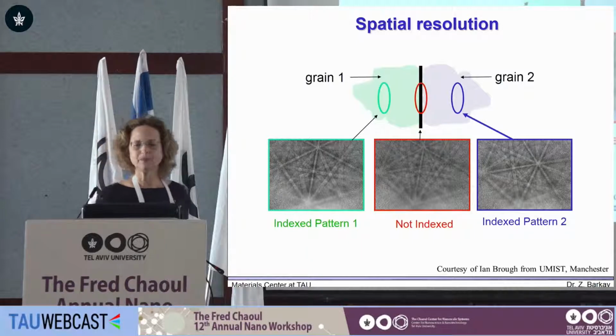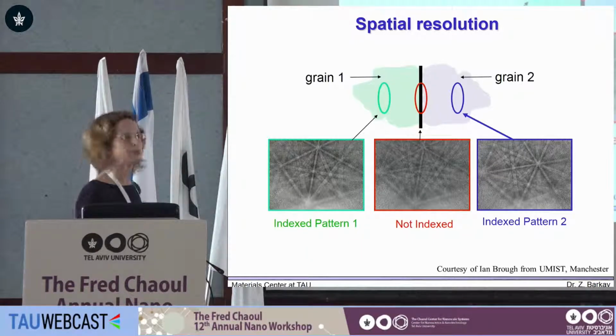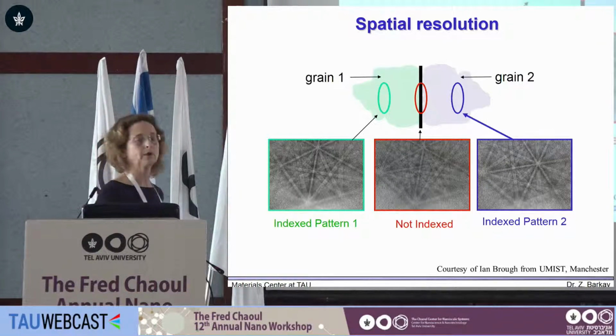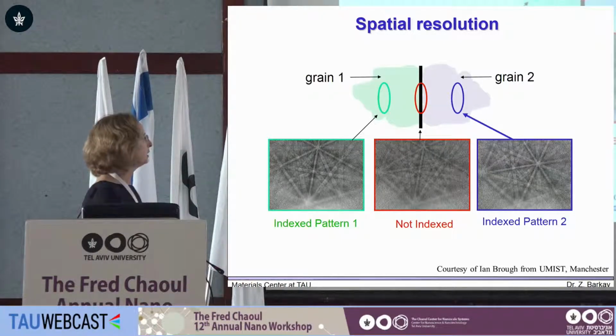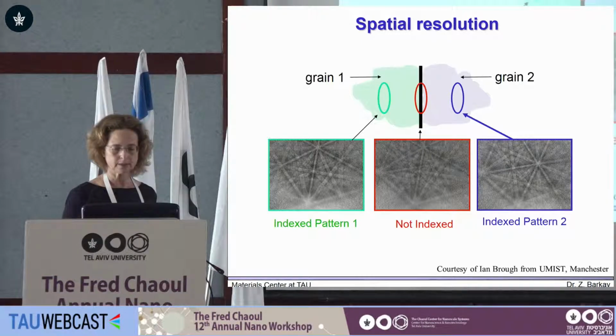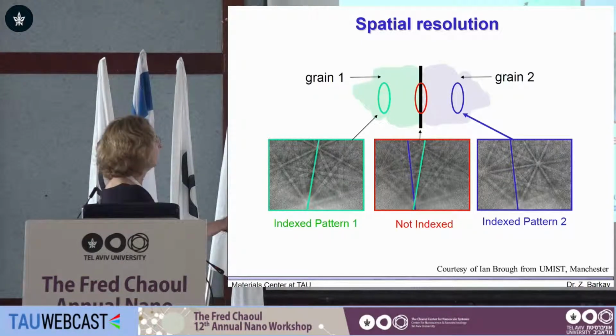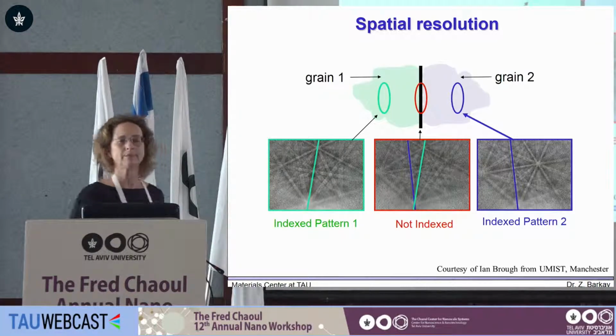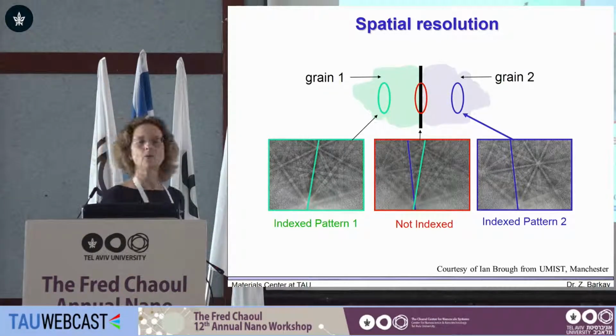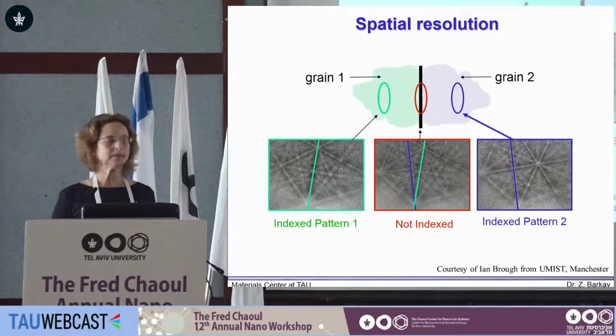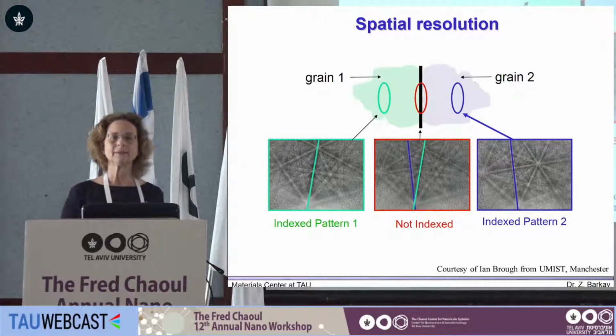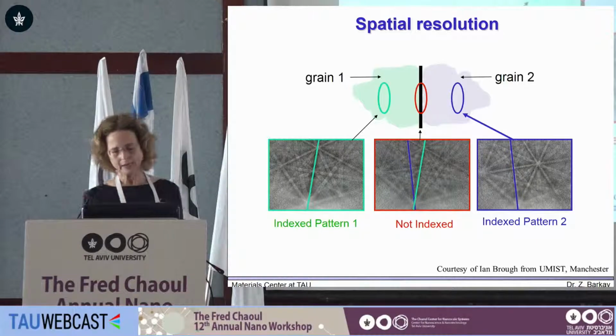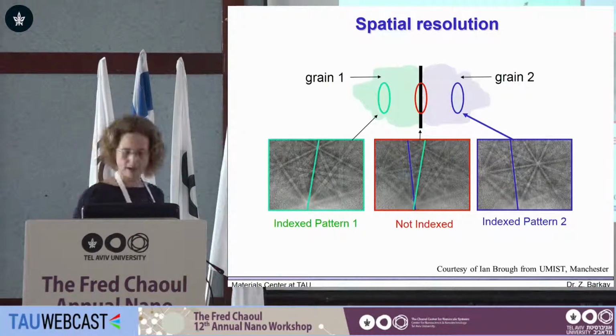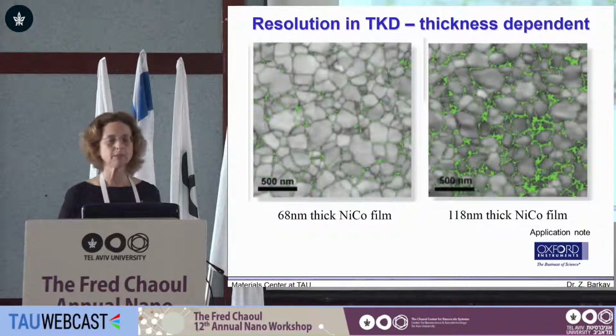So how really to specify the resolution? It is usually specified both for reflection and transmission over a crossing grain boundary. This is one grain with one solution - this is the Kikuchi pattern - and we have another grain with the other solution, but at the interface we have overlap. This overlap is not well resolved by the algorithms, and it actually dictated the resolution. But now algorithms are becoming better, and hopefully we can somehow overcome this.